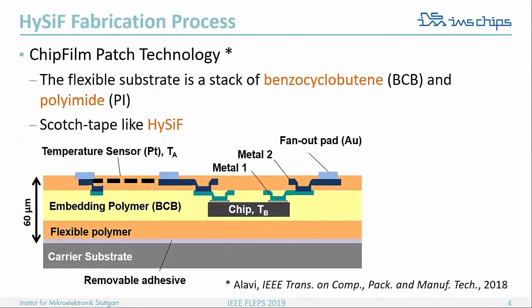So chip film patch technology is mainly a stack of two polymers. So polyimide as a flexible polymer provides the flexibility of the package, and BCB, benzocyclobutene, is also spin coated. It provides reliability of our package, and also it's CMOS compatible, so outgassing problems don't affect the chips. And the chip here is embedded in this technique. It's a sandwich structure, and on top we can fabricate our sensors or our organic transistors or any other active or passive component.